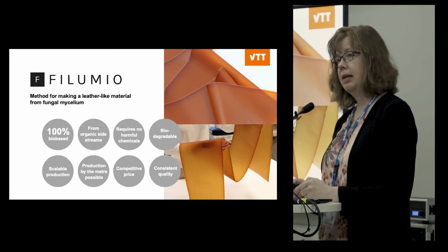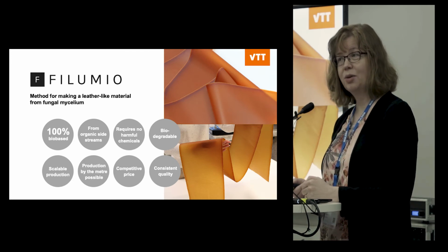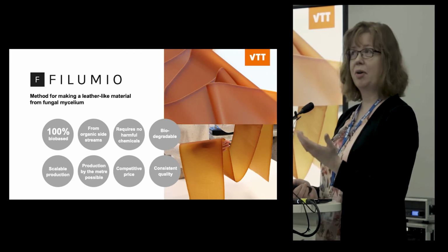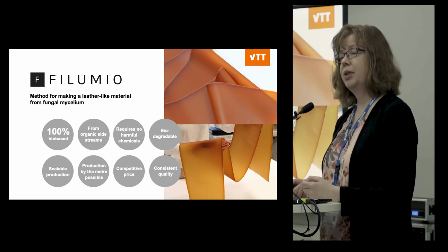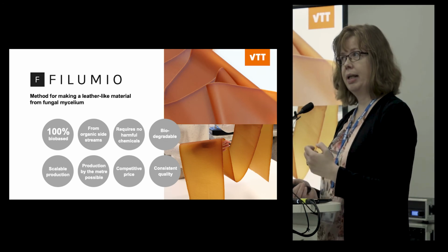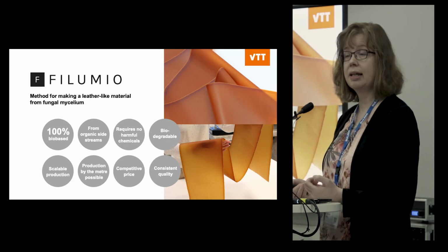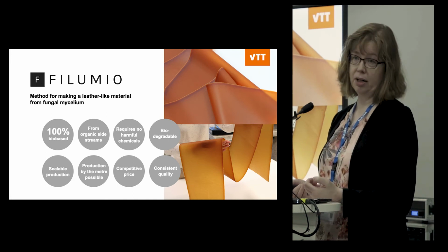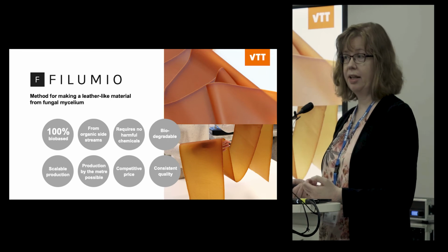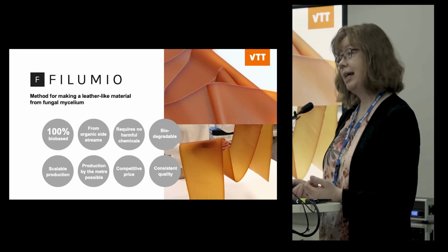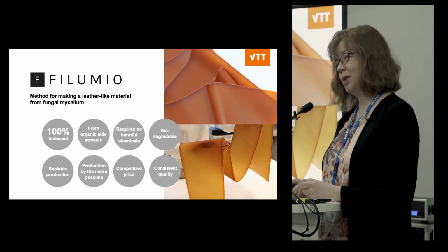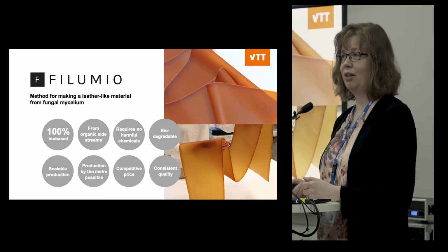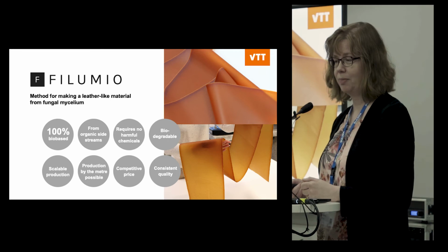And the quality is quite consistent, and if comparing again to bovine leather, the material properties in terms of tensile strength are similar to bovine leather. But if we think about the tear strength, we are not quite there yet, so there is still a need for research.